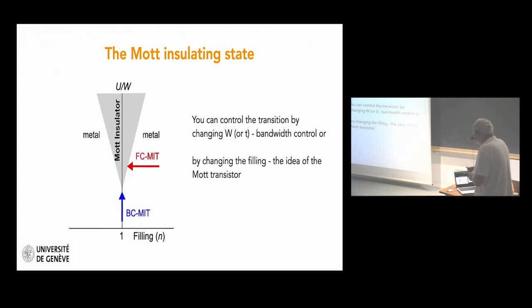If you trace the Mott insulating state as a function of filling, so here it's half filling, and U over W, you see that you develop this Mott insulating state in this gray region. And you see here that you can access or leave the Mott insulating state by changing the bandwidth or the interaction, but you can also leave the Mott insulating state by changing the doping.